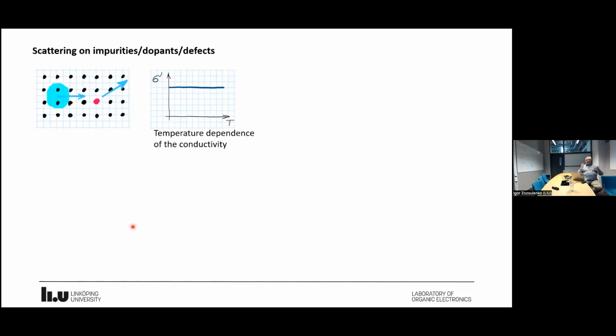And this means that resistivity in the system, as we discussed previously, is determined by the non-ideality of the system, like impurities, dopants, defects, etc. So scattering on impurities, dopants, and defects is one of the most important mechanisms of scattering. If you have a wave packet, it scatters off the impurity, and this is the reason for resistivity of the system. And when you calculate or measure the temperature dependence of conductivity, you will find that this does not depend on the temperature.